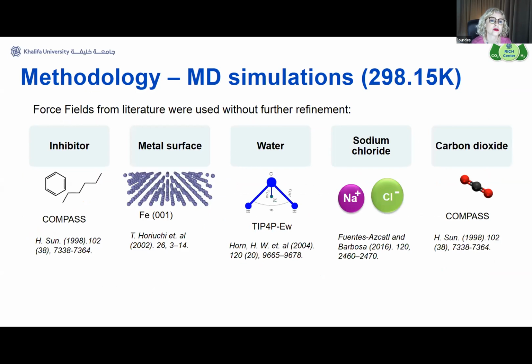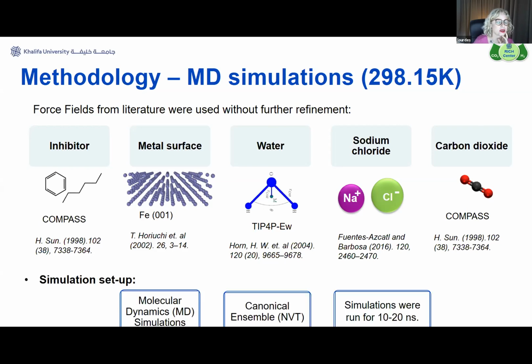and all the results I'm going to show you today were done at one temperature, 298.15 K, which is essentially the temperature at which this experiment should happen. The force fields we used were taken from the literature. We didn't refine any force fields. For the inhibitors, we have used the COMPASS force field. For the metal surface, we consider iron 001. The water model we use is the TIP4P-Ew because it's the one that has the same level of interactions as the COMPASS that we were using for the inhibitors. And then we have also modeled the sodium chloride and the carbon dioxide. Carbon dioxide also with COMPASS to be at the same level of approximation, and sodium and chlorine from a force field from Fuentes, Alcázar, and Barbosa. Then we have done molecular dynamics simulations in the canonical ensemble, and our simulations were run for a minimum of 10 and, on average, about 20 nanoseconds.